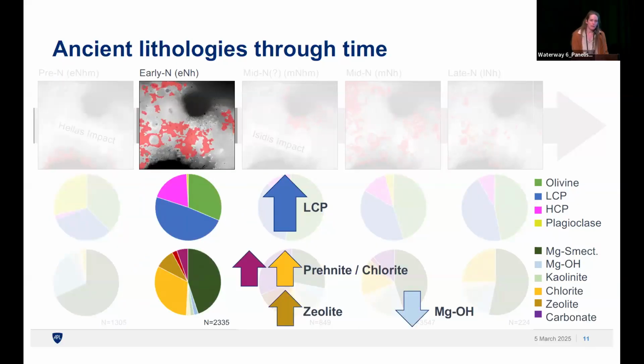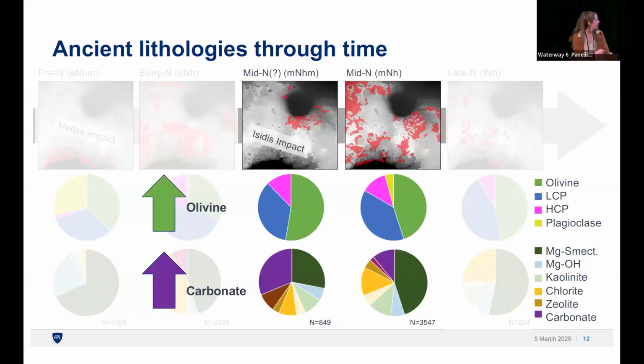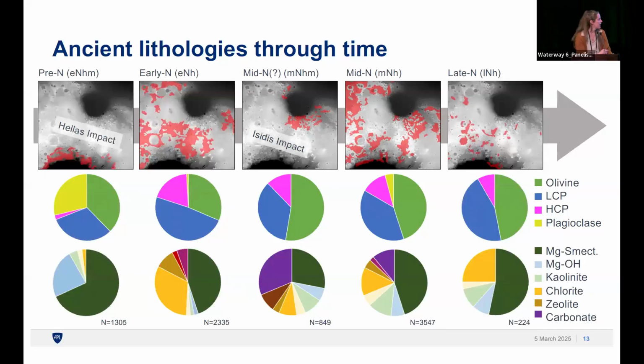Into the early Noachian, we get an enhancement in low calcium pyroxene, and the alteration is dominantly prehnite, chlorite, zeolite. And all of these alteration phases form at elevated temperatures and in hydrothermal settings. And so this is telling us something about the alteration during the early Noachian period. As we move into the mid-Noachian, we sample the material that's surrounding Isidis. And so we see a big enhancement in the olivine signature, which corresponds to the olivine carbonate unit that surrounds Isidis basin. And of course, we see a parallel with the carbonate signature as well, mostly in the unit that surrounds Isidis, but also some carbonate in the rest of the mid-Noachian terrains. And then lastly, we have the late Noachian, which we have less sampled, so I won't really harp on that here, but it's pretty comparable to other Noachian aged units.